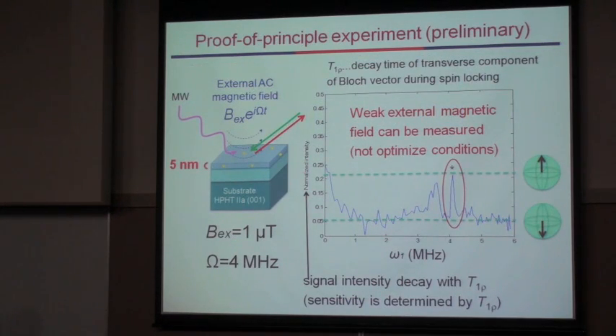So this is a preliminary result. You can see the peak at 4 megahertz. This corresponds to the external field measurement. So we can demonstrate for the first time by using the spin-locking technique in our sample. This is a very preliminary result. So the experimental condition is not optimized.